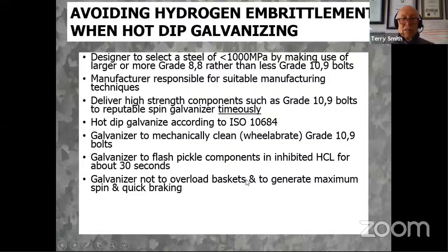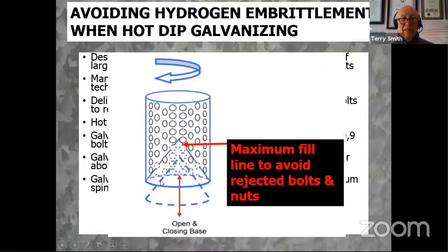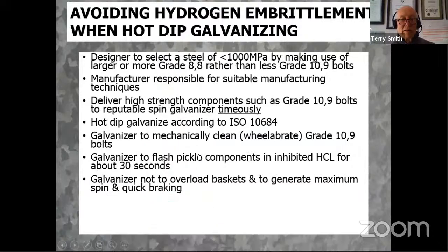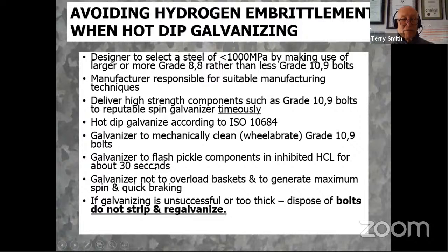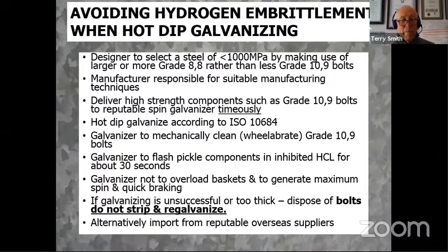Galvanizer not to overload the baskets, to generate maximum spin and quick braking. You can see again the maximum four points, so we can actually get a rapid spin of the items rather than them not spinning at all. And if hot dip galvanizing is unsuccessful or too thick because of overloading, dispose of the bolts and do not strip or regalvanize, because that can create major hydrogen embrittlement problems.